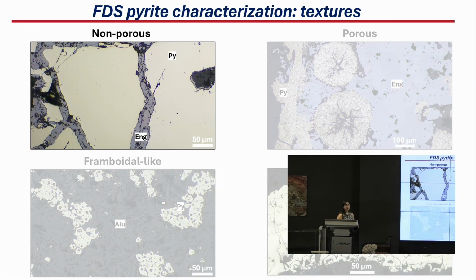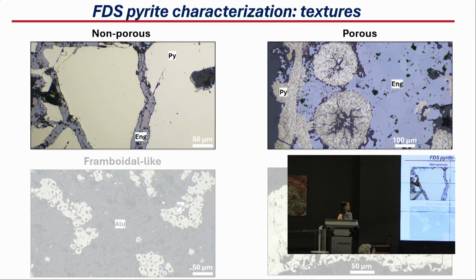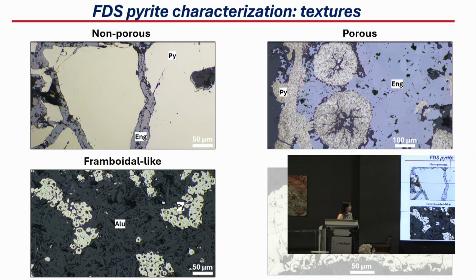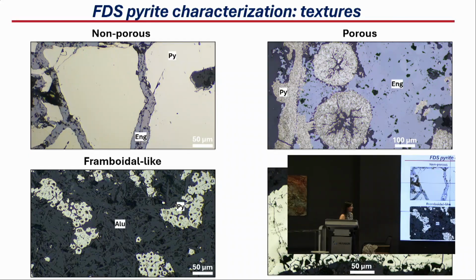Now I will show some of the different pyrite textures we have seen in Filo del Sol. We grouped them in 4 main groups. First, something that we call non-porous pyrite. As we can see, it's a crystalline pyrite, in this case surrounded and pulsated by enargite. Then we have what we call porous pyrite. As you can see, the texture changes. It's also called spongy pyrite in the literature, and it's also associated with enargite. We have something that we call framboidal-like and framboidal-derived pyrite, and not framboidal by definition, because it doesn't follow the strict definition for framboidal pyrite. And finally, we have a colloform pyrite type, which is overgrowing a non-porous pyrite crystal and has this distinctive texture.